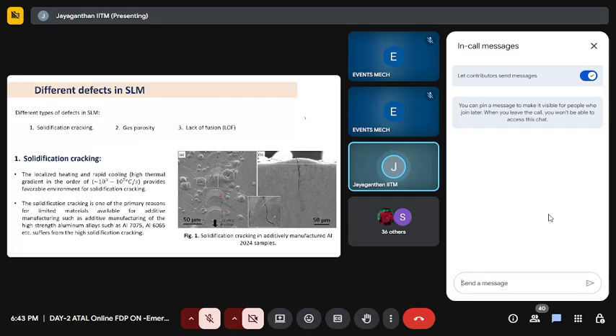And this is one of the major reasons we are not able to print different aluminum alloys like 6061, 7075. We always end up seeing this problem because of very rapid cooling, differential expansion and contraction. You always end up seeing there is a crack inside. This we call solidification cracking. Because of the liquid to solid transformation, obviously because of the very high cooling rate imposed, there is differential expansion and contraction leading to the formation of the crack. In casting, internally, you might have some cracks actually. One of the major issues.